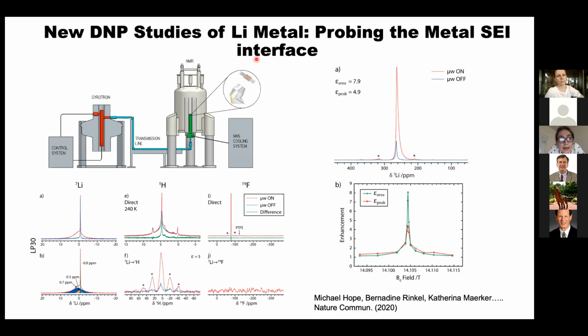So you could use the unpaired electrons in lithium as a source of polarization. And Charlie Slichter and his group 10 years later actually showed this experimentally. This was largely forgotten about until we looked at this last year. We showed that if you blasted the lithiums with microwave power, you could get a significant enhancement of the lithium metal signal by, in this example, 8 times. We've had up to 10 and 20 times if we increase the power. That was essentially the experiment done by Charlie Slichter 50 years ago.